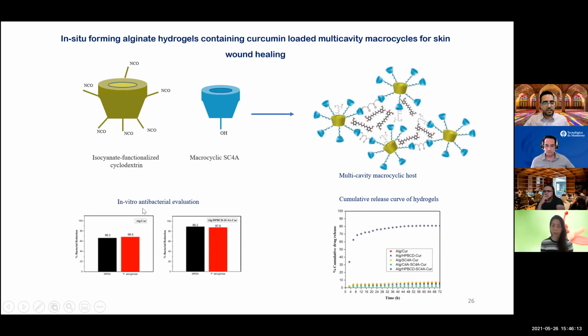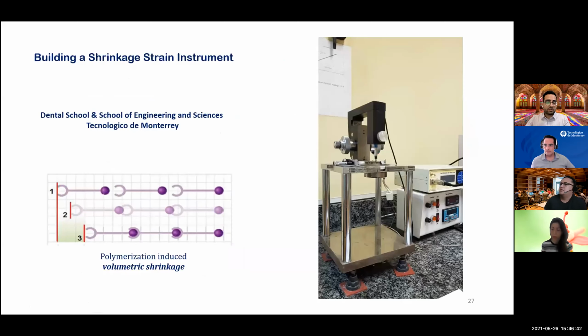The other thing is that we again did an antibacterial evaluation, and as you can see here, the first one is only alginate containing curcumin. The second one is the alginate with curcumin already incorporated in this multi-cavity host, and you can see here that we have more than a 20% increase in antibacterial activity, because using this multi-cavity host can enhance the efficiency of the host-guest interaction.